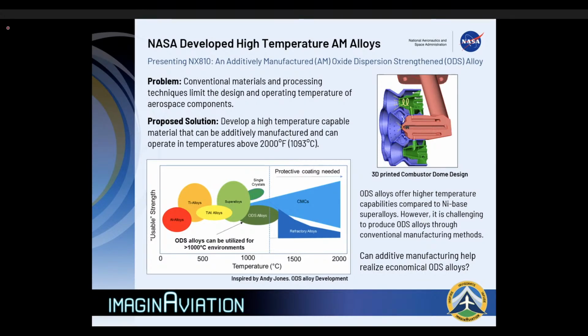And we sat down real quick, and the answer that we had was no. No, there isn't, actually. And maybe that's something that we should look into and see if we can't develop a material that we could 3D print for these new combustor domes. And so, when we went and looked at the drawing board, the issue is that the temperatures they want to operate at, 2,000 degrees Fahrenheit, is a very extreme temperature, especially at atmosphere. And if you look at the conventional metals used in aerospace, aluminum, titanium, and even your high temperature superalloys, they just don't have the properties to be able to withstand and survive those extreme temperatures. And so we're really limited about what type of materials we can use for this application.